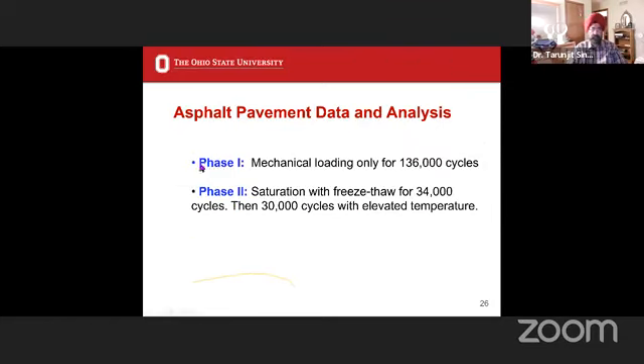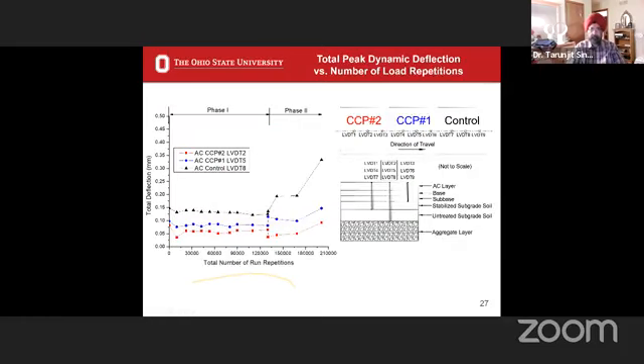I think in one of the sketches for the asphalt pavement I talked about each pavement first had 136,000 cycles, and then water was allowed into the pavement after 20 years of traffic, and then we did saturation of freeze-thaw, and then another 30,000 cycles for elevated temperature testing. So by the time we were done with this, you can see that we had a little more than 30 years of highway traffic, that is structural loading on the pavement for the asphalt.